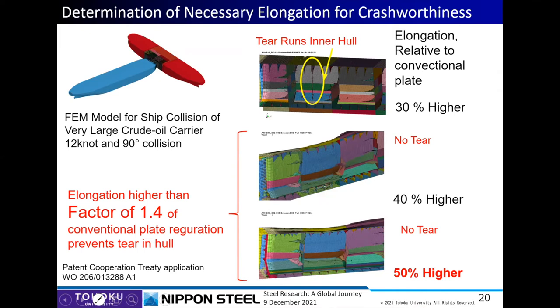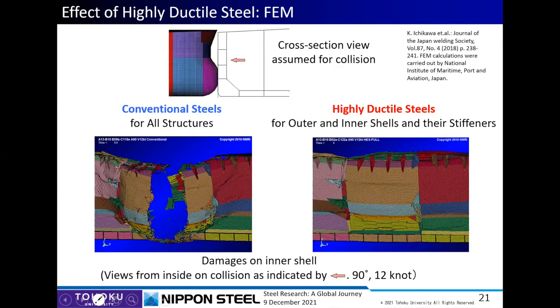I'll show you a higher resolution picture here. We assumed this colliding scenario. This is the colliding ship and this is the collided ship. This picture is an image from the inside of the collided ship. In the case of conventional steels, you can see this kind of large tear on the ship structure. But if you apply highly ductile steels, you don't have any tear on the hull structure.